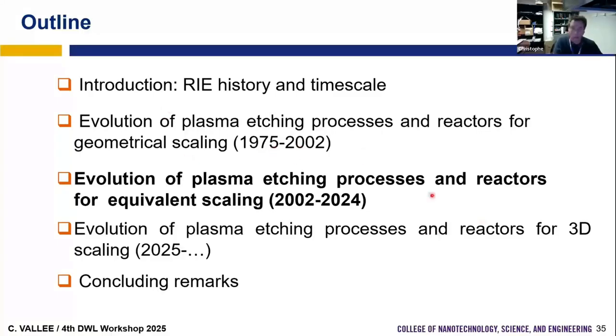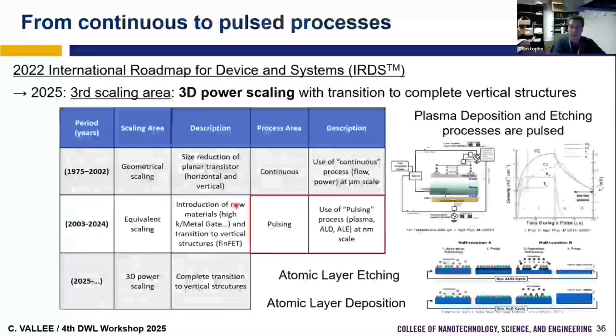Now we go to the second part, which is the evolution of plasma etching processes and reactors for equivalent scaling. For the equivalent scaling, this is where we introduce new materials and we transition to vertical structures. So we had the FinFET, for example, for the transistor. What we can observe is that we started to pulse. Regarding plasma etching, we started to pulse the plasma. And after we started to pulse also the precursor. So the idea is that now we have a decoupling of radical flux, ion flux and ion energy.